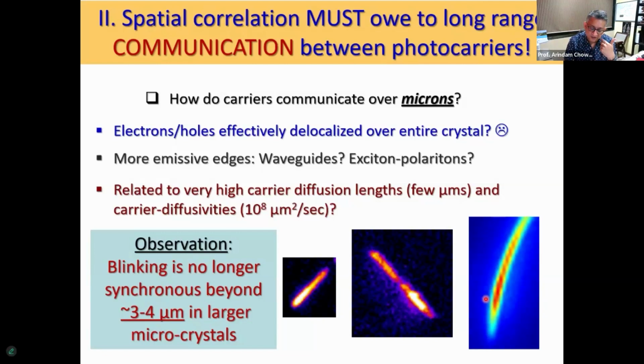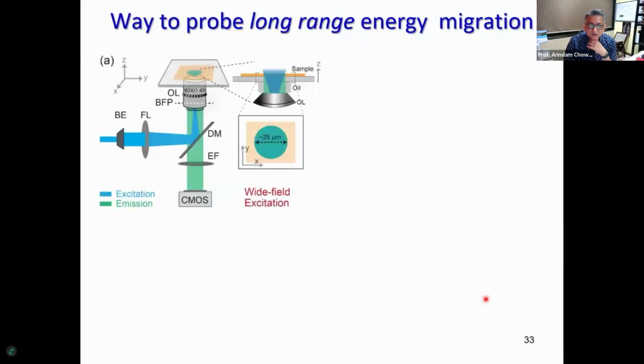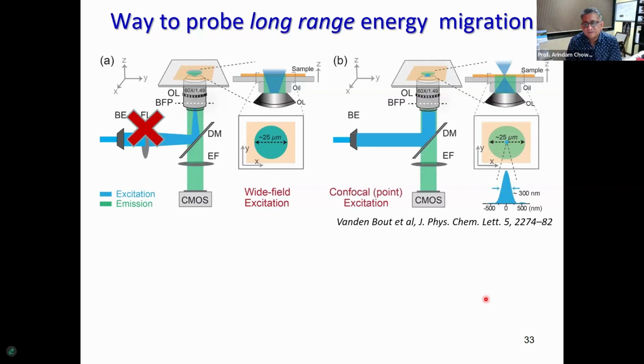All right. So we explored this idea: is it possible that it is actually about the correlated motion or the correlation diffusion of carriers? So how do you test that? How do you really test such long range energy migration? Here we are talking about microns, okay? We are not talking about nanometers or tens of nanometers or even 100 nanometers, right? So what we found out in the literature is a very nice, simple way from Professor Vanden Bout of U Texas Austin, and there's another connection. He happens to be either a postdoc or a graduate student of Paul Barbara, whom I respect a lot.